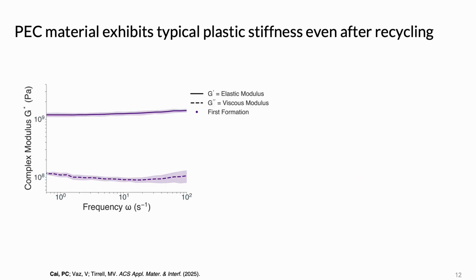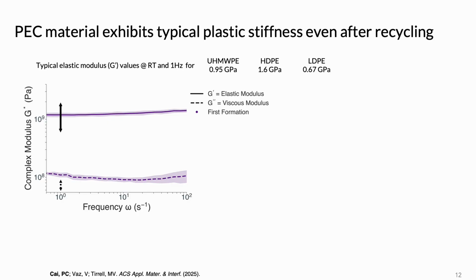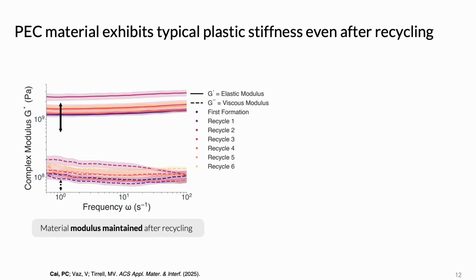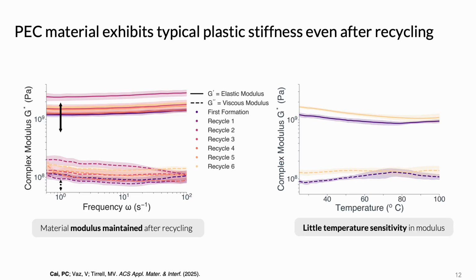Given that plastics must hold up in applications like packaging, it's important to characterize the mechanical properties of these biopolymer-based materials. Here I'm showing the elastic and viscous moduli, which are metrics that denote the stiffness and fluidity of a material across 2 decades in frequency, and for reference, I'll also put here the ranges for elastic and viscous moduli of commercial polyethylene. The biopolymer PEC exhibits a modulus within the range of what polyethylene exhibits across 6 recycles, and not only that, the material behavior is retained across multiple recycles and up to temperatures as high as 100 degrees Celsius.